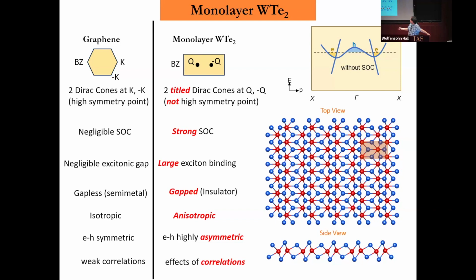Graphene is very isotropic. But you already see from the lattice that tungsten ditelluride is very anisotropic. You can think of it as a zigzag chain, or a rectangle with an aspect ratio between the A and B directions.